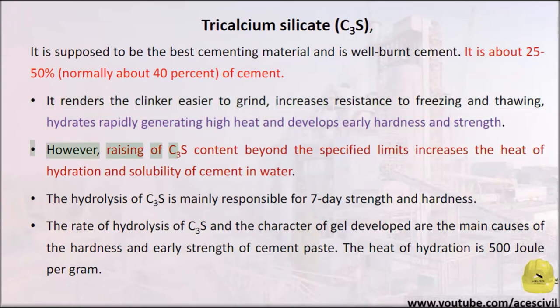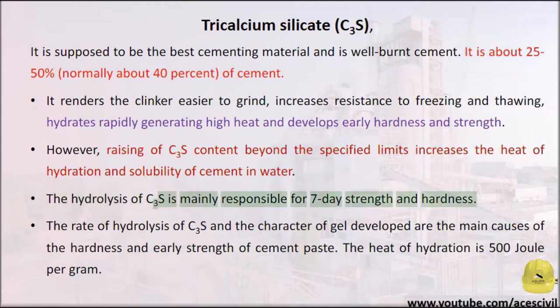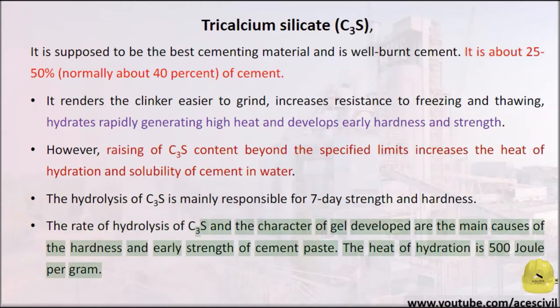However, raising the C3S content beyond the specified limits increases the heat of hydration and solubility of cement in water. The hydrolysis of C3S is mainly responsible for 7-day strength and hardness. The rate of hydrolysis of C3S and the character of gel developed are the main causes of the hardness and early strength of cement paste.